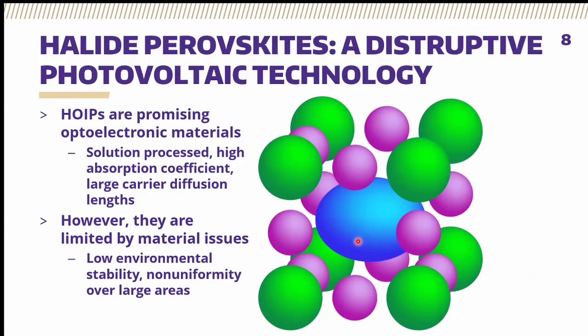And the material that I want to use as an alternative PV or next-gen PV material are these halide perovskite devices. These perovskites are very promising optoelectronic materials for a number of different reasons, most promisingly because they can be deposited from solution. Unlike a traditional PV technology, these materials can be dissolved in common organic solvents, meaning that in theory you could print these solar cells as quickly, easily, and as flexibly as you would print a newspaper every morning or something like that, allowing for massive amounts of throughput and at very low cost.